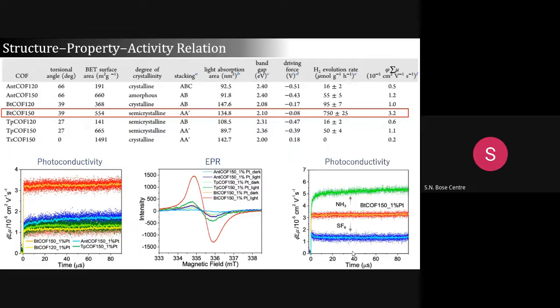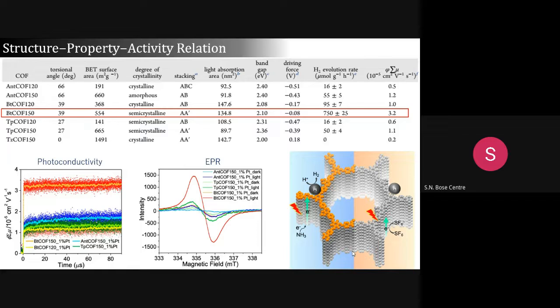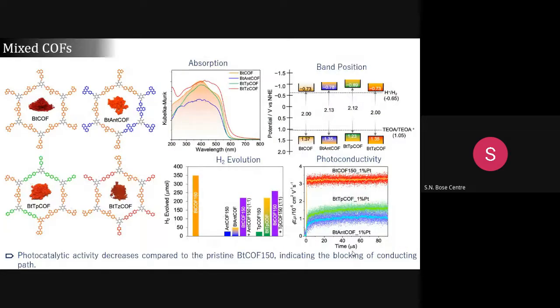Here we have also tried to understand whether this is because of the electron or the hole. So we put ammonia and SF6. Basically, SF6 can scavenge the electron, whereas ammonia can scavenge the hole. And you can see the BtCOF150 is basically an electron transporting material and can do the hydrogen evolution. Further, this is just a pictorial representation. Our best copolymer is the BtCOF150.